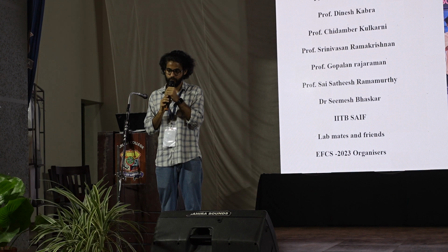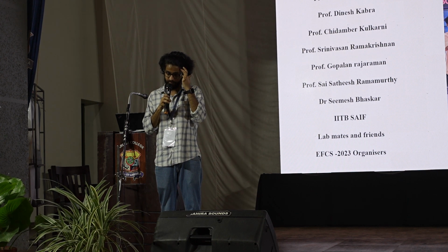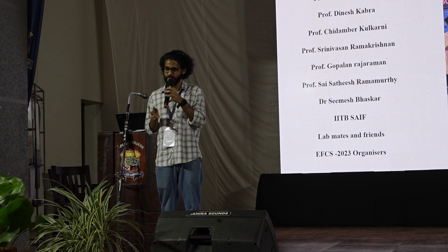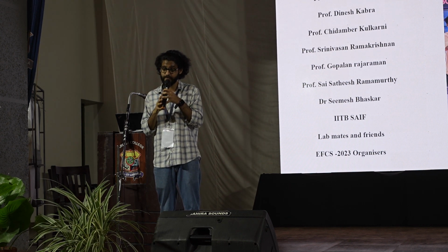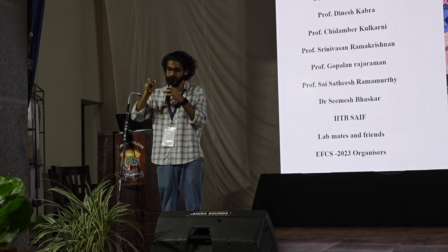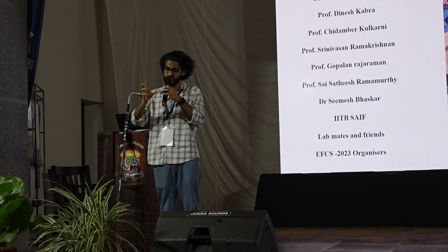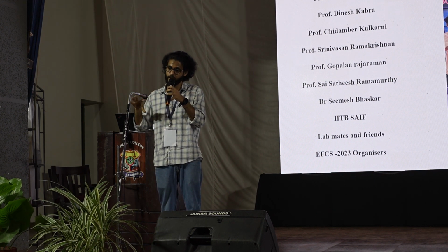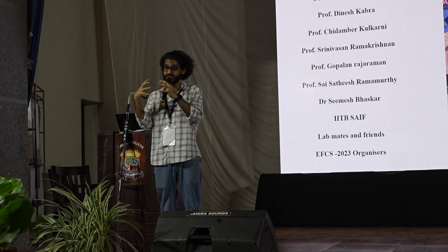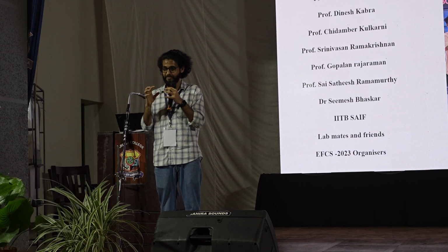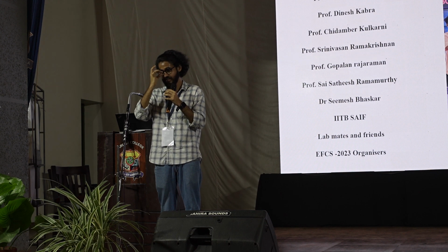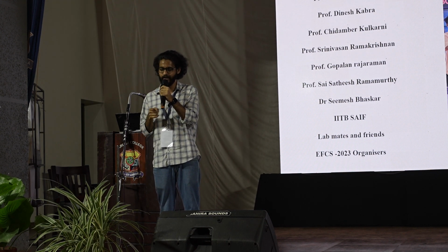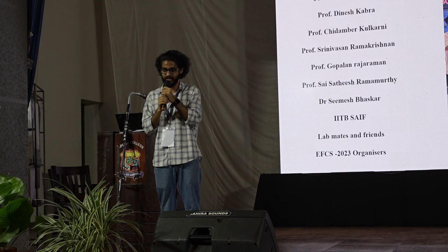And secondly, you also mentioned silver-gold alloys, along with the silver and gold. How did you confirm that? We confirmed from EDAX elemental mapping. If it were core-shell, we could easily distinguish where is silver and where is gold. But in our case, in the EDAX elemental mapping, we are observing a homogeneous distribution of this. A homogeneous mixture cannot confirm an alloy. I think we can confirm from the diffraction pattern as well. Have you done anything? Yeah, we have done that. I haven't tested it.